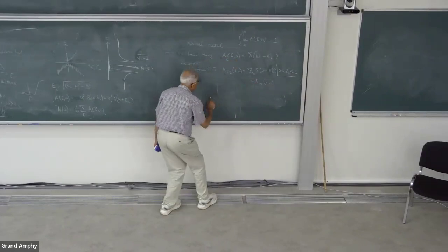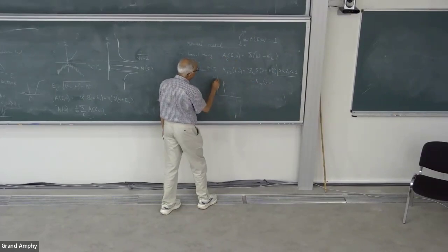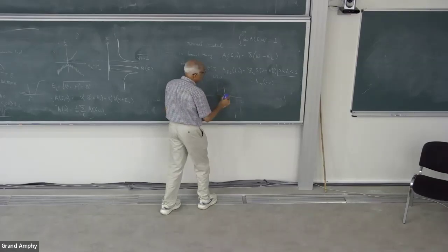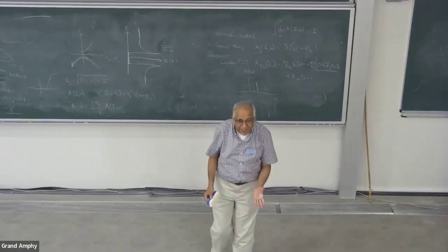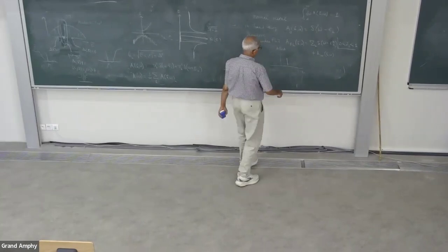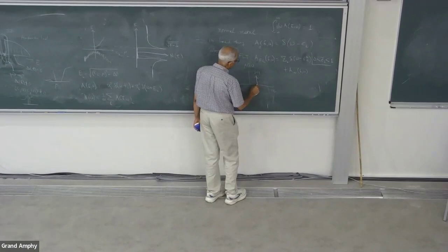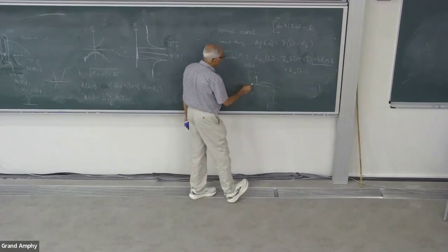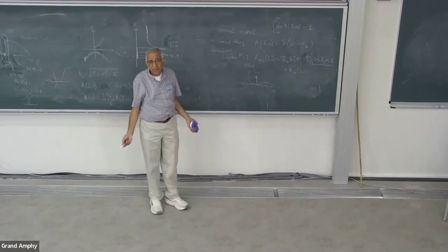So instead of the spectral function looking like a delta function, I'm plotting A(k, omega) for k fixed as a function of omega. In heavy fermion materials, Z could be a number of order 10 to the minus 3. So it can be vastly reduced Z. And then there is stuff, and all of this stuff must take up the weight of 1 minus Z to satisfy the sum rule.